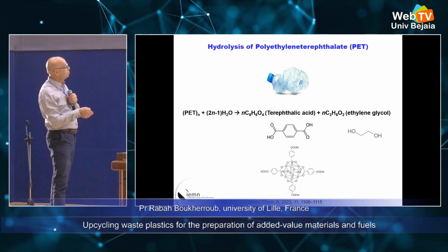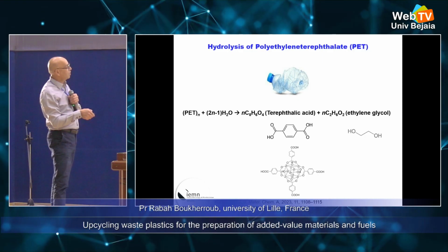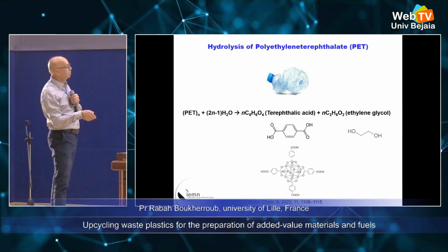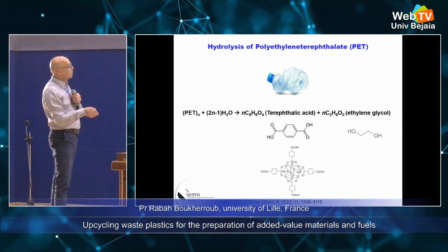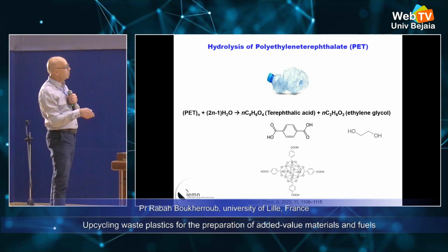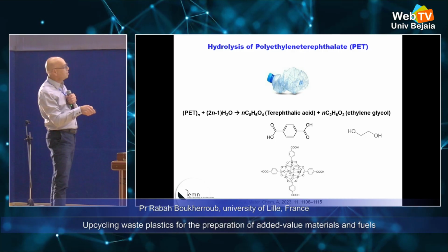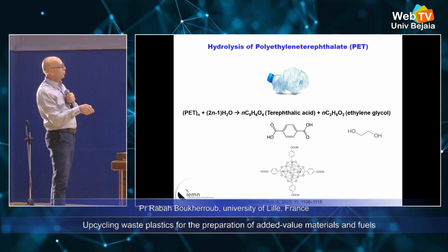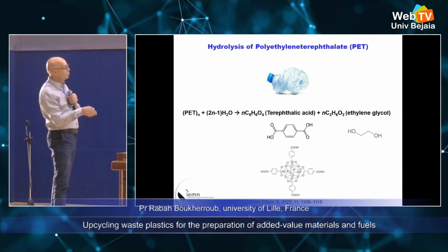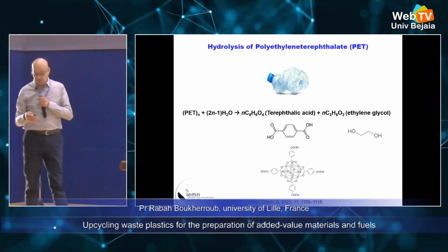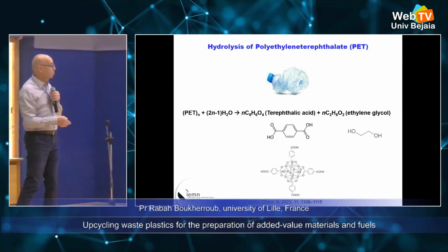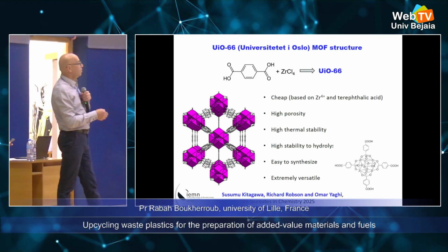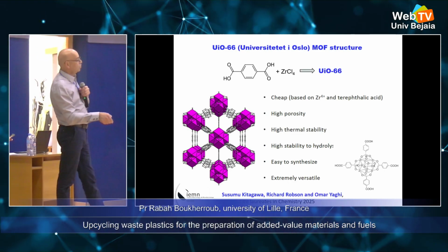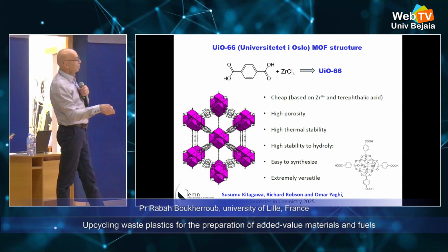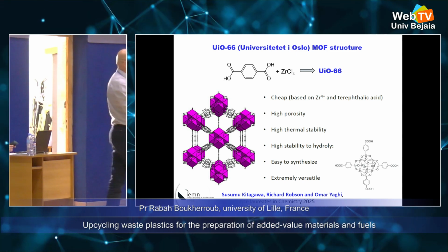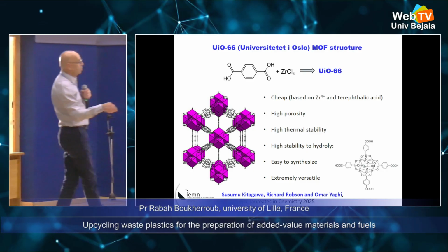So here is exactly how you do it for a chemist. When you hydrolyze the PET, you generate terephthalic acid and ethylene glycol. This is one of the initial ligands for making MOFs. So if you add any salt from transition metals, you end up making these very nice and crystalline materials called metal organic frameworks. You can see the recent Nobel Prize in chemistry for these three scientists on MOFs.